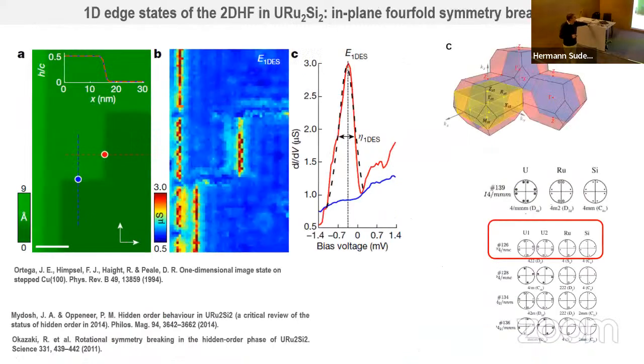But of course, there is a fourfold symmetry. Now, there has been quite some debate because there were some people who said that, okay, maybe there is a twofold symmetry inside the hidden order. But the difference was very, very tiny. And later they showed that this twofold symmetry is not there. So there is still fourfold symmetry inside the hidden order. So our suspicion is that inside the bulk, there is still fourfold symmetry. But for some reason, maybe valence changes close to the surface or whatever happens, there is a twofold symmetry appearing close to the surface.